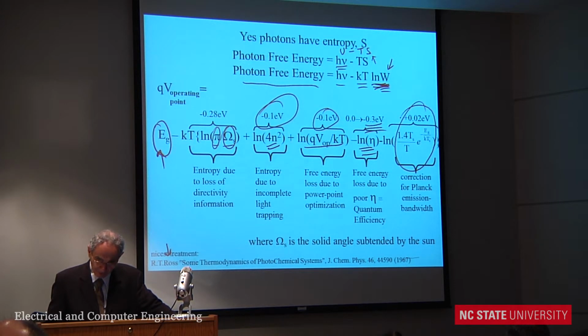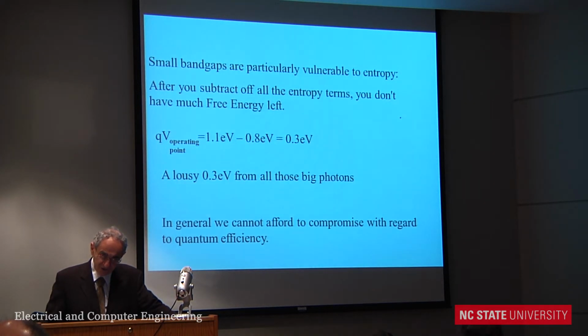I'll skip that. So what it tells you is you've got to be very careful with the voltage. If you start with the band gap of silicon, 1.1 volts, and you subtract all those entropy terms on the previous slide, they add up to 0.8 of a volt, and you could end up with a crummy 0.3 of a volt at the operating point. And that's pretty sad, considering that you're starting from 2-volt photons. That's really quite sad. So what it says is you cannot mess around with the voltage. You can't just sweep it under the rug. You've got to do a good job with the voltage.